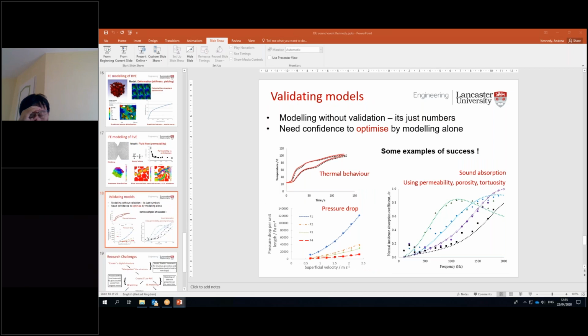So modeling without validation is just numbers, or indeed numbers and pretty pictures. We need the confidence that we can apply a high level of modeling to develop optimization without a very large need on producing samples. And we've had some good examples of successes in modeling thermal behavior, pressure drop. The models are the lines, and the experimental data are the dots, and they match up very well. And also had some good successes around sound absorption as well.